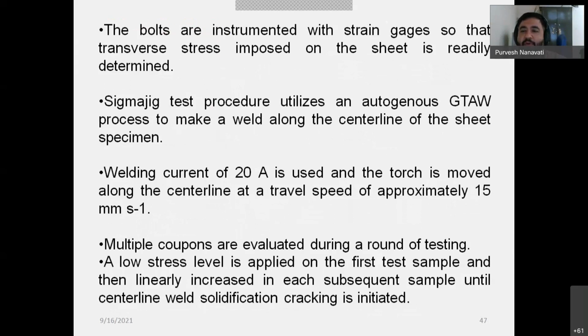And this test is produced by an autogenous GTAW process to make the weld on the center line. And a welding current of 20 ampere is used, and the torch travels along at 15 mm per second. And not only one but multiple coupons you can evaluate, and in a round of the test when you run this qualification test and go for multiple coupons, you have to identify the low stress level for the first test sample. Then this will be linearly increased in each subsequent sample until a centerline weld solidification crack is initiated.